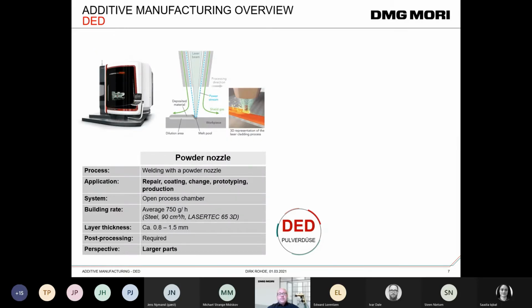The DED works differently. You have a nozzle head in the center. You have the laser to bring the heat to result in a melt pool. There you blow the powder onto the melt pool, and that is more or less covered by a shield gas. So that's a laser welding process.